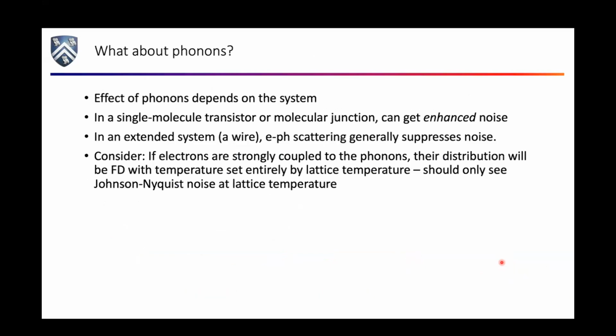Okay. So what happens if you have phonons? Well, phonons can be bad for these measurements. Phonons can basically smear things out and suppress the noise. And in fact, one limit to think about is, imagine if the electrons talk to the phonons super, super strongly, then all you're ever going to get for the electron distribution function, even though you're trying to drive it, is a Fermi-Dirac distribution at the temperature of the lattice. So all you're going to see is Johnson-Nyquist noise at the lattice temperature, so you're not going to see any extra noise when you drive the system.